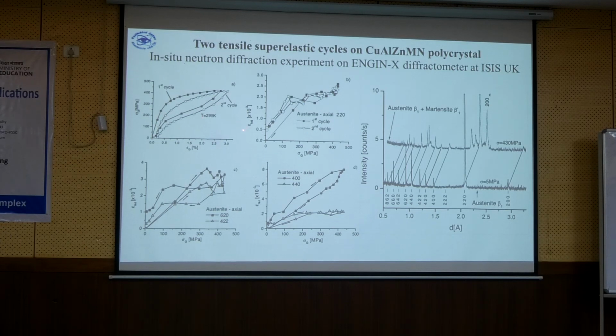In this figure we show the information from the peak shifts, and at the same time the intensity. These are the peaks. This is the austenite. This is the martensite without stress, under large stress. So the intensities are changing, you see it, but also the peak positions are changing. And if you evaluate the peak position, you can see that in the elastic range, from 0 to something like 300 megapascal, 200 megapascal here, it's approximately linear. This is as it should be in elasticity. If you have elastic deformation, the peak shift is proportional to the stress. This is the first line up to somewhere like 300 megapascal.